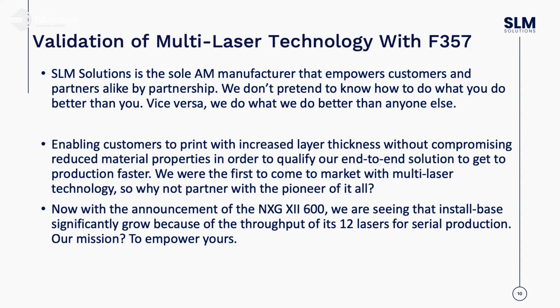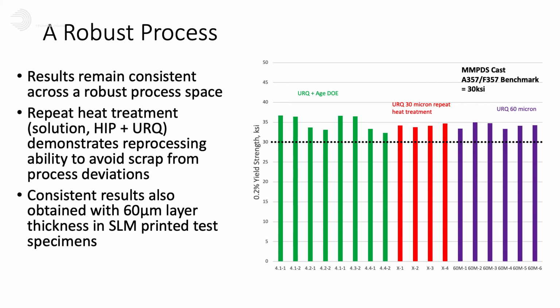And the regulatory agencies require that we have the burden of creating performance-based data that says we can do it repeatedly over time. And that's why these experiments that we're doing here with the University of Arizona are so very, very important. And we're also doing it with NASA, and we're doing it with NIST, and with other government third-party agencies. We're putting our reputation on the line. If these things crash and burn, Andrew is required to tell the truth. He's going to tell you what they are. But we have empirical data to show that 60 microns produces the same material properties as 30 microns.